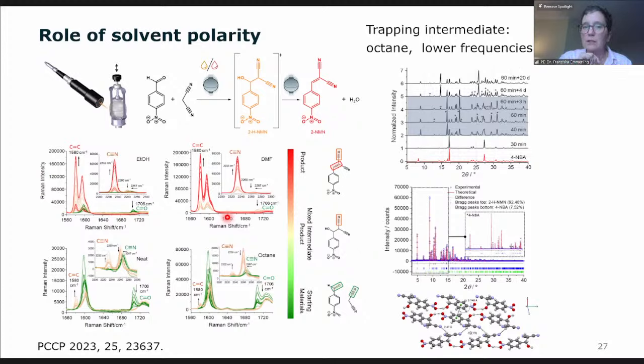It does not necessarily make the reaction slower. If you add a solvent, usually the reaction proceeds faster. But if you, for instance, refer to non-polar solvents, it can also be in the same range. Of course, this particular reaction on this slide is slower because we have this intermediate formed, and then it takes more time because the solvent doesn't help in that case.